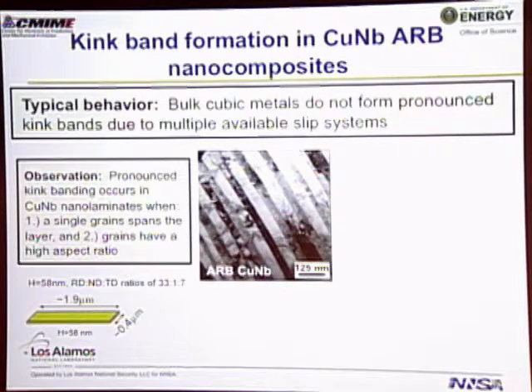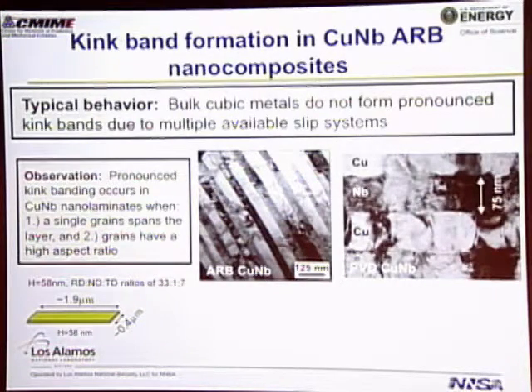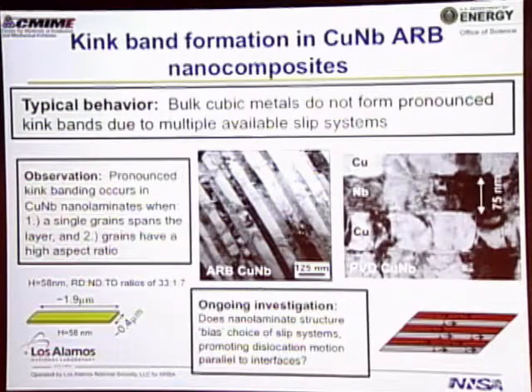In our case, what we've done is made a geometry that's layered like this that only has a single grain across the thickness, and these grains are like big pancakes, so they don't have any boundaries within the layers. Contrast that with the PVD material, where you've got lots of boundaries within the layers. And as such, we think what's happening here is that the nanolaminate structure is making these dislocations only want to move in certain directions parallel to the layers, and as such, you start seeing these new deformation mechanisms.